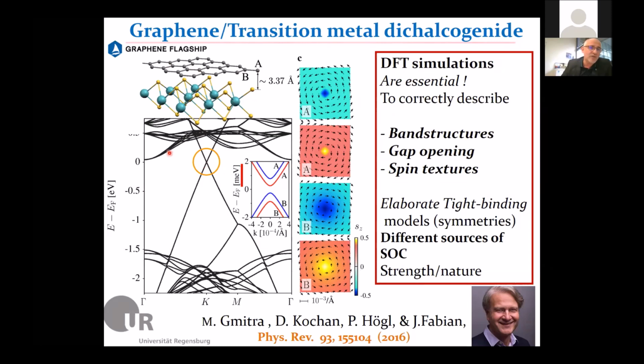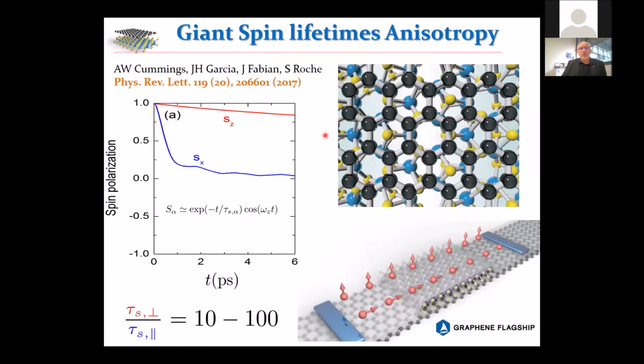So you can avoid any charge transfer or absorption. You can also tune with the gate and absorb inside the bands of the TMDs. But you have changed graphene. Graphene has become something different, with a spin texture that it doesn't have otherwise. What we figured out is that this specific imprinting of the spin-orbit coupling into graphene will lead to a